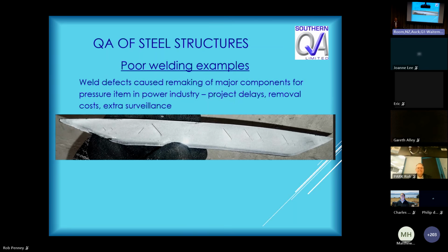Poor welding examples. What do we get in poor welding? This is relatively recent. These are weld defects. Now, this is what's called a boat sample, aptly named because in a longitudinal weld, you cut the weld preparation out in a boat shape, like a dugout canoe shape, and then you cut it down the centre line. So this is showing the defects on the centre line of the welds. And this is called chevron cracking. It's characteristically at 45 degrees to the surface.